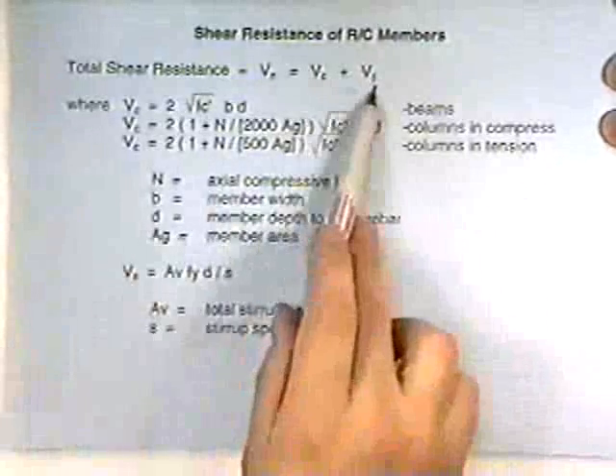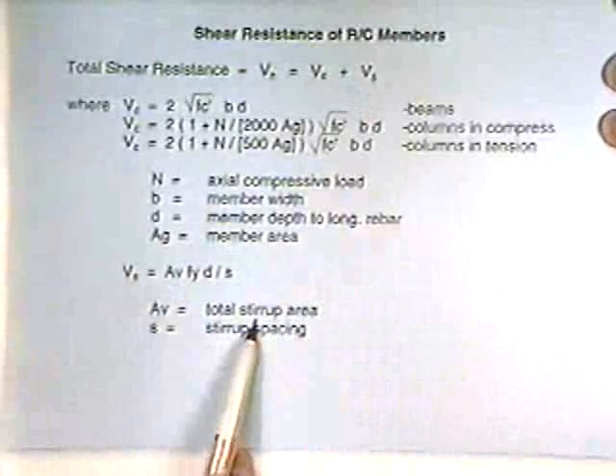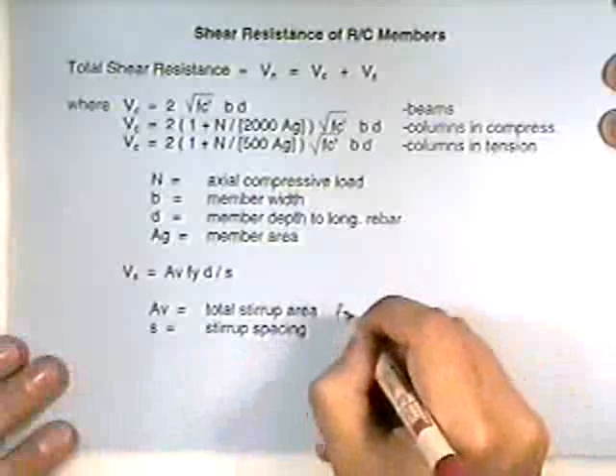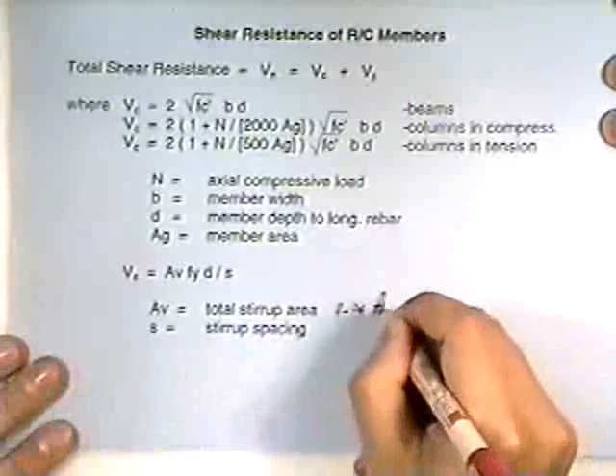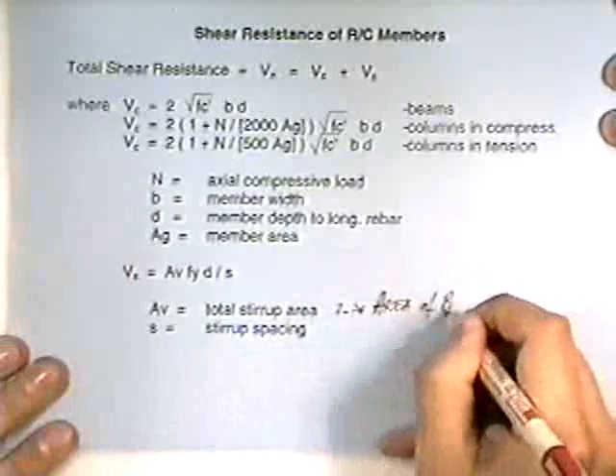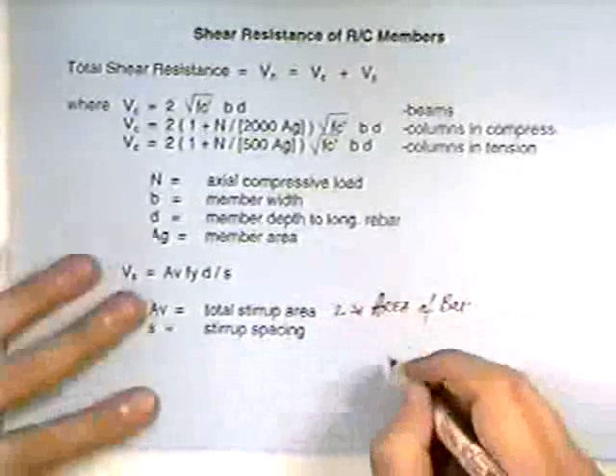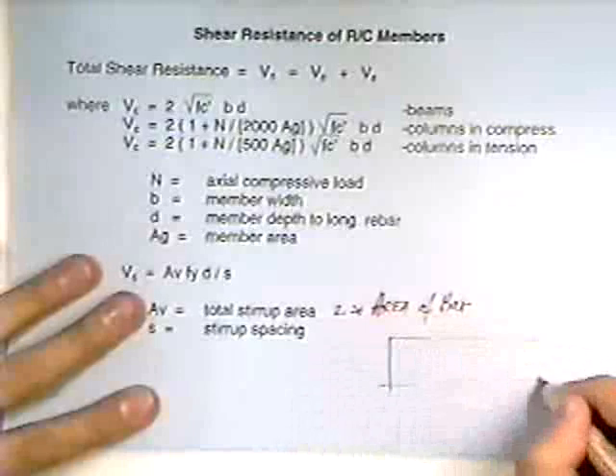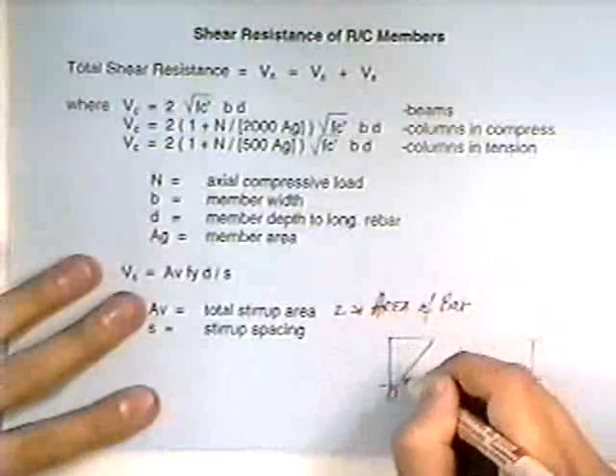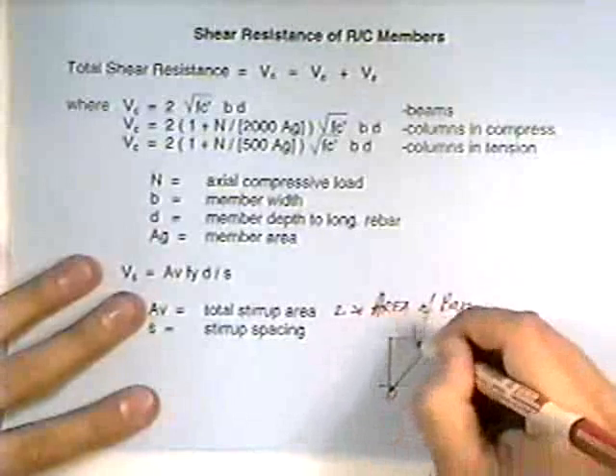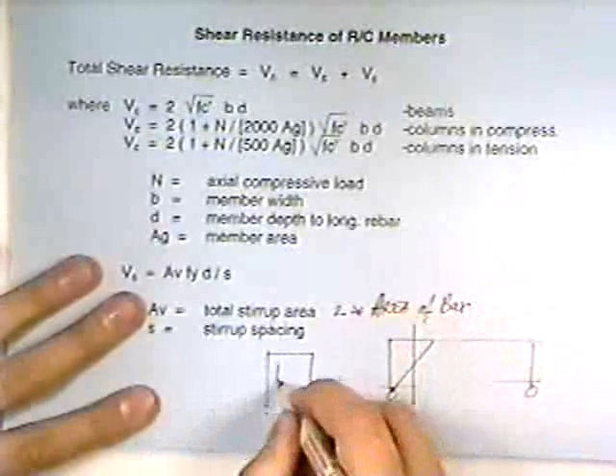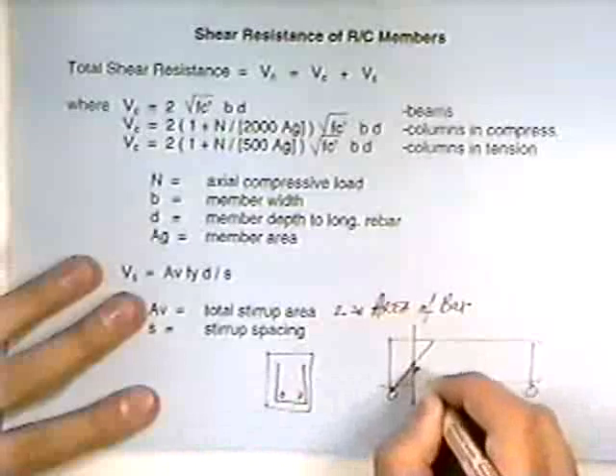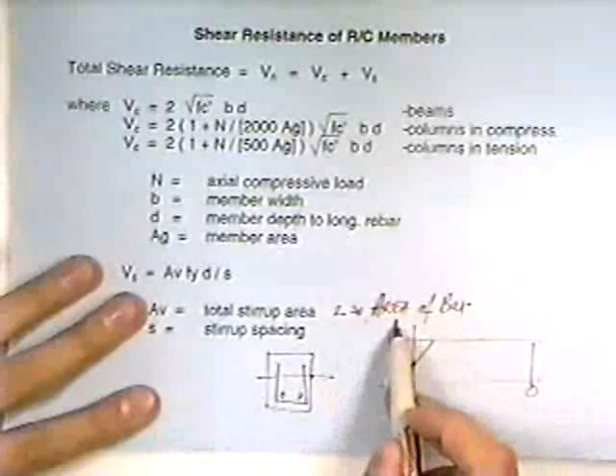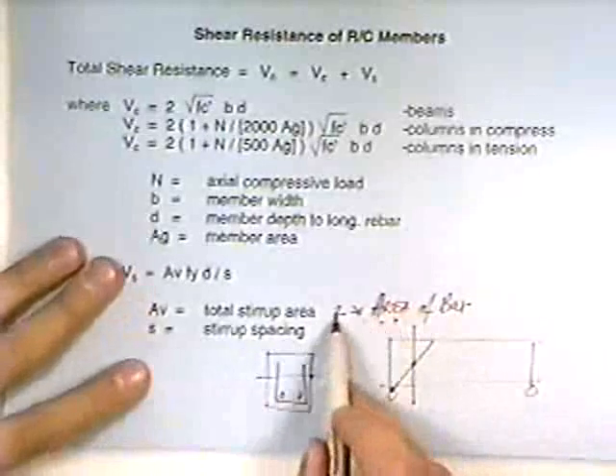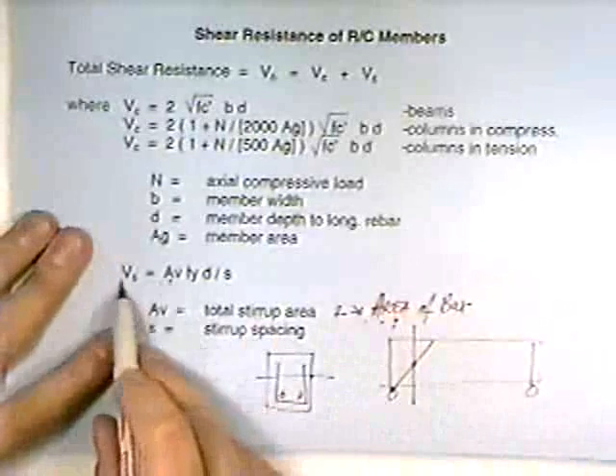Everything else here you know. The V sub S is based on the area of the stirrup. So if you're using a number 3 stirrup, basically you're going to have 2 times the area of the bar. Because for that beam to fail in shear, if you've got a simply supported beam, cracks are going to develop this way in shear. And if I look at one section, there's my stirrup, this crack is going to go through both of these bars. So that's why you have 2. So if you're using a number 2 or number 3 bar, you're going to be using 2 times 0.11 in this formula.